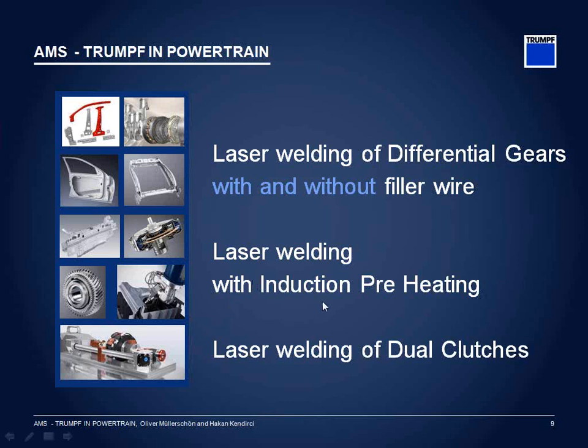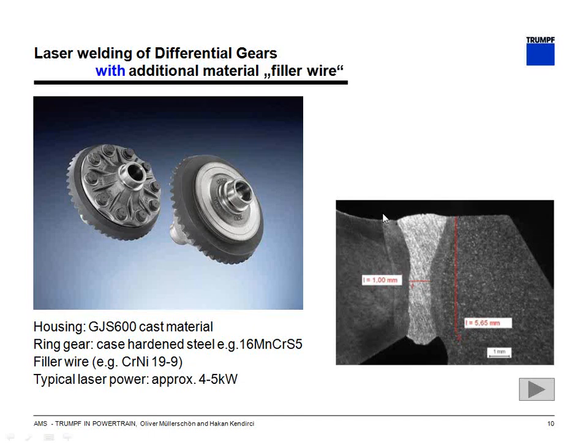Laser welding with an induction preheating system is sometimes necessary when we have parts, or two material partners, with a high carbon equivalent. Then we can also use our equipment for preheating prior to the welding process. The last one in this part is laser welding of double clutches, where we can show you a cross-section of such a double clutch with a lot of different laser welds made with our systems.